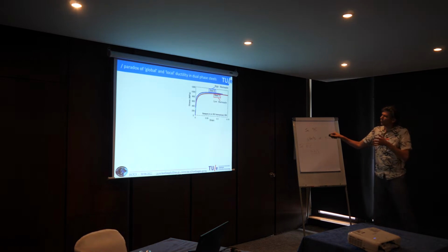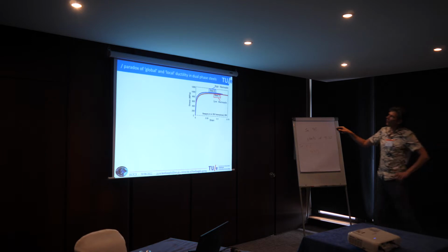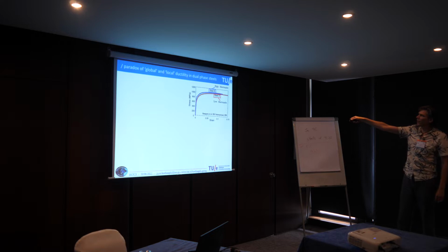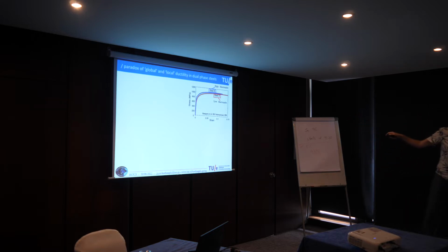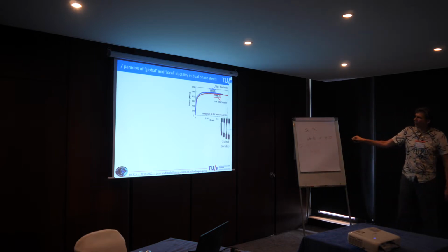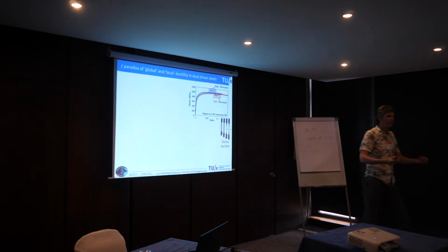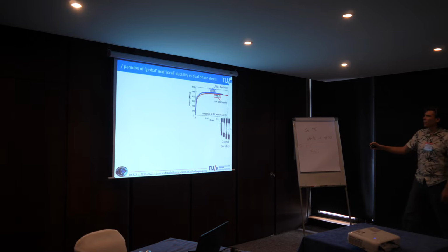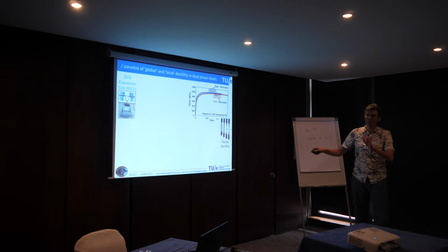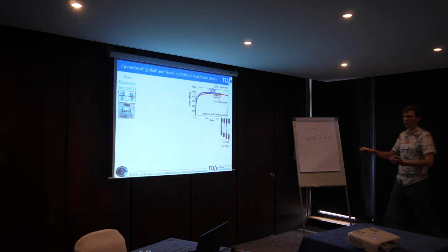So this is some earlier research, 2004, where they basically looked at two steels that have the same ultimate tensile strength, and clearly steel A should be superior because it has a much larger total elongation. But this has been tested in a uniaxial tensile test, and basically here you're testing for global ductility, so the behavior to resist necking. But you can also do a different type of test, like a hole expansion test. As you create a hole, you come in with a punch, and then at some point a fracture will occur. And that's more like testing the local ductility.